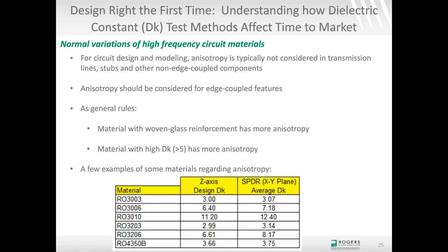Most circuit designs that are not edge coupled are usually not that sensitive to anisotropy. For a transmission line circuit, the electric fields are mostly using the Z axis, so how much different the dielectric constant is on the XY plane doesn't usually affect that. Of course, there are fringing fields that pick up a little bit of the XY plane for a transmission line. But the big issue normally is edge-coupled features, like a microstrip edge-coupled bandpass filter or edge-coupled directional couplers and things like that. That's usually where anisotropy comes into play.